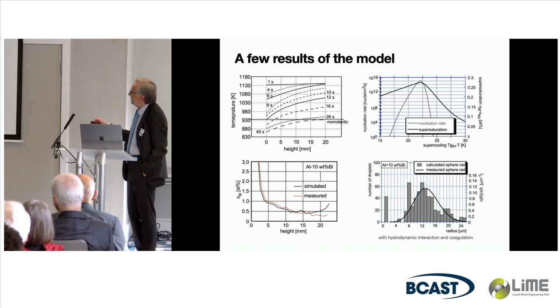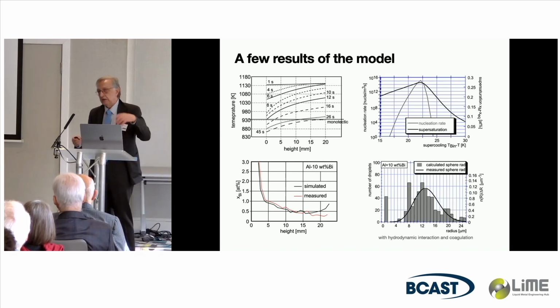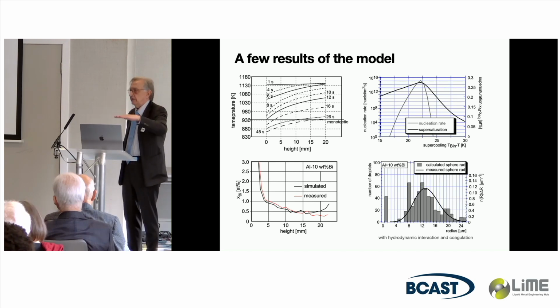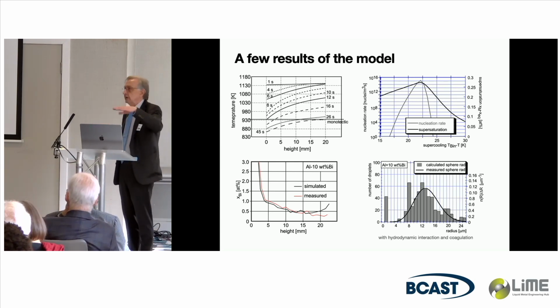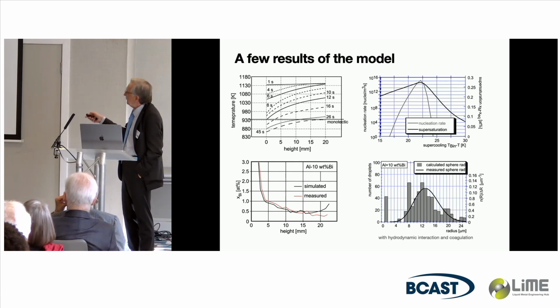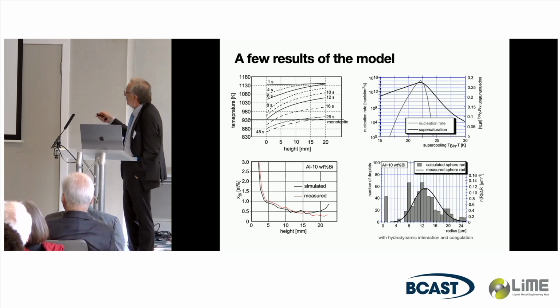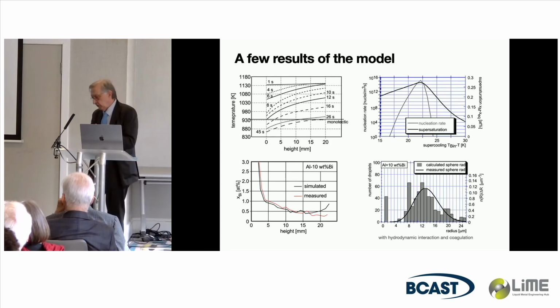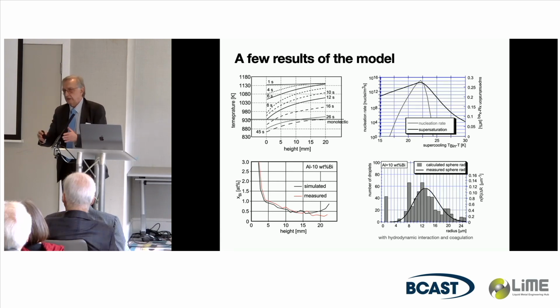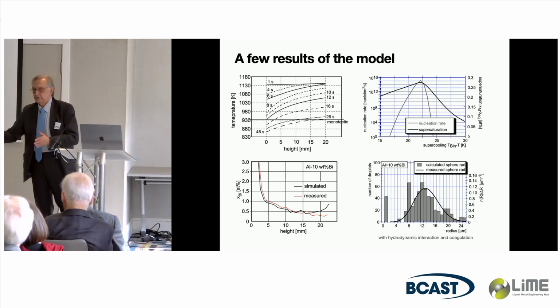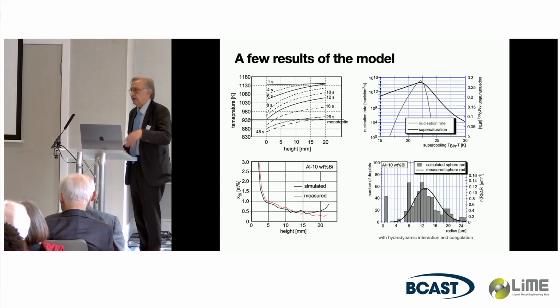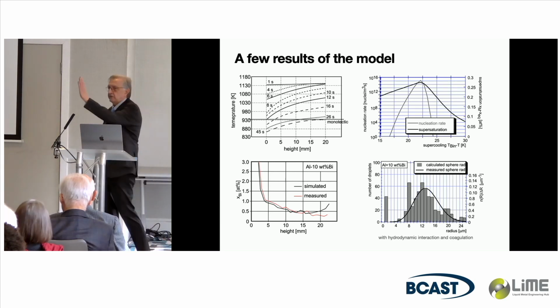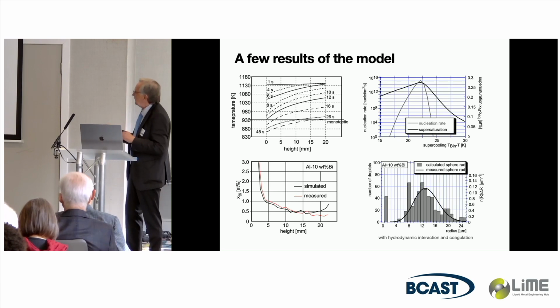Okay, so this is the temperature field. The same we did in parabolic flights with aerogels, we did in the lab. So we knew exactly when we started solidification, and we did it unidirectional in an aerogel cylinder. And you see, if you follow this by infrared cameras, it takes some time before the solidification front really is through the whole sample of 20 millimeter length. So then you have a nucleation event, here only one recorded. It can repeat as much as the solidification front proceeds. There can be one nucleation event, it proceeds a few millimeters, a second nucleation event, et cetera. It's a complex interaction of concentration fields, decreasing supersaturation, drops move, increasing supersaturation. It's really complicated. So you can have periodic nucleation of droplets.